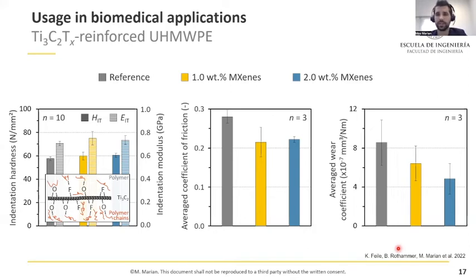Also the mechanical properties and higher hardness certainly play a substantial role. And it is expected that the MXene reinforcement promotes the crystallinity and a more hydrophilic character of the surfaces, which leads to reduced frictional shearing due to the lower tendency for degeneration of attached proteins. But at this very moment, we are further qualifying the crystallinity of the composites, the wettability, the wear mechanism, the biocompatibility in terms of cytotoxicity and so on. So there's still a lot to explore in this direction. However, we already saw some potential of reducing, for example, the wear of polymeric materials like we have them in tibial inlays, and thus the risk of associated inflammation or wear particle induced aseptic loosening of the implants.